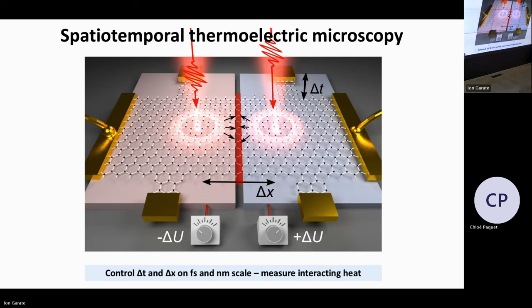Yeah. So in this case, when I was talking about symmetry breaking, it's not crystallographic symmetry breaking. It's device symmetry breaking, on a different level. Basically, you need to have a different Seebeck coefficient on both sides of the junction, and that is what breaks your symmetry and generates a net current in one direction. If you just have a channel, you can generate heat and charges will move, but they will move radially away, so you don't get any net current. So it's really symmetry breaking on a device level. Regarding TMDs, I'm not sure if someone has done it, but in principle, you could get the same effect. If you can make a p-n junction, the only thing is that there are other photogeneration mechanisms that will probably dominate, like the photovoltaic effect. In this case, the photovoltaic effect is very small. You're really dominated by the photothermoelectric effect because you have such efficient heating of the electron system and a large Seebeck coefficient.